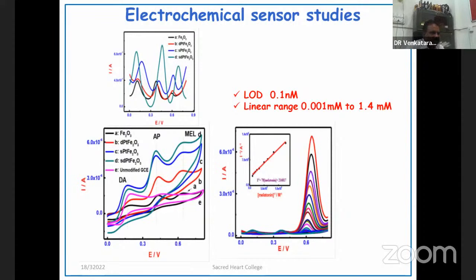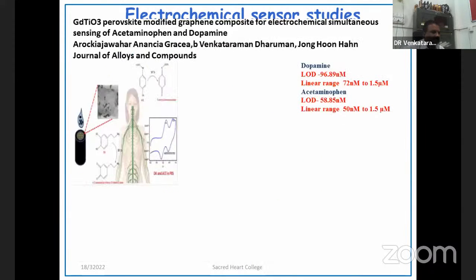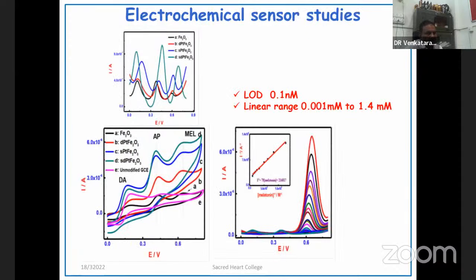Then you have to estimate the linear range and the lower detection limit. In our study, 0.1 nanomolar is the lowest concentration of dopamine detected. And this is the linear range up to which your current increases with concentration. In another application, as I told you, when you change the material, you change the linearity or the sensitivity. Sensitivity, again, is the slope.